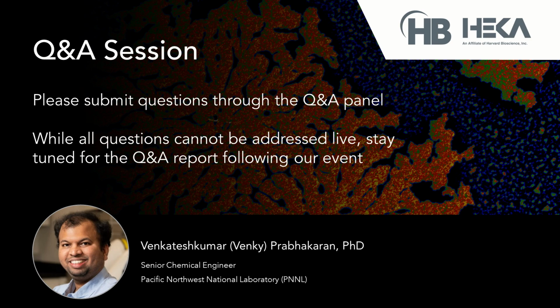Yes. Usually after you land the tip and make a measurement, the product is left on the surface, and you really need to understand what reaction you are doing. For example, in the case of corrosion, you cannot do a very long measurement, because it will form a very thick product layer, and sometimes the product can be picked up at the tip end and affect the next measurement.